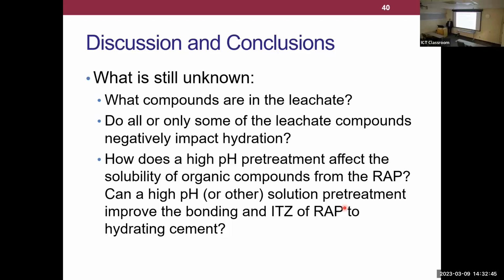And the other thing we never really figured out is, what is the sodium hydroxide solution really doing? It's doing some sort of surface modification. We're seeing more organic compounds in the leachate, but then we also saw a slight increase in strength. So again, those don't quite align with what we were originally thinking here.